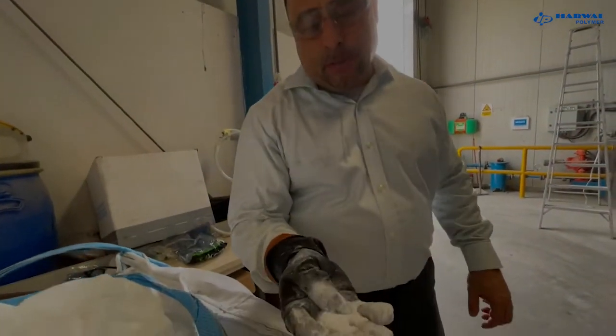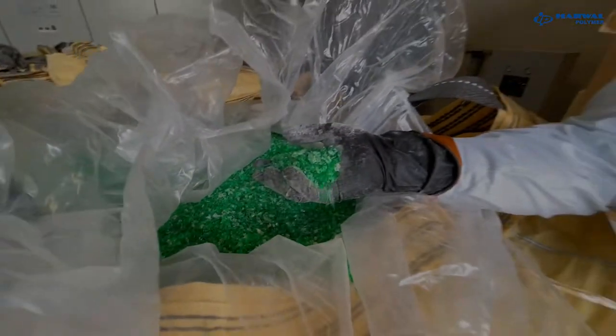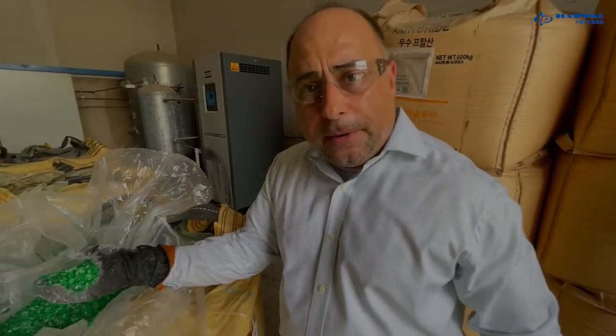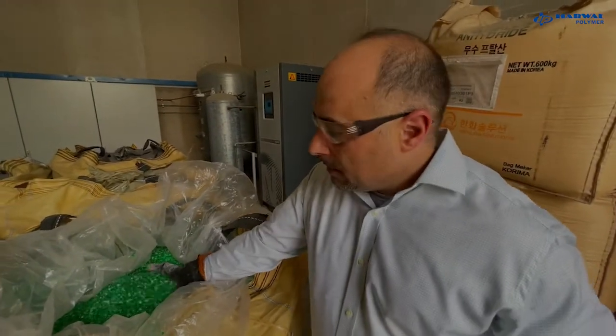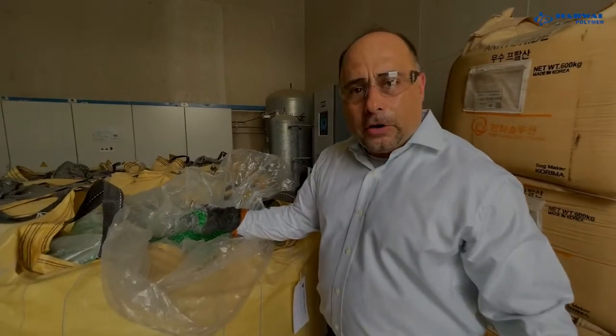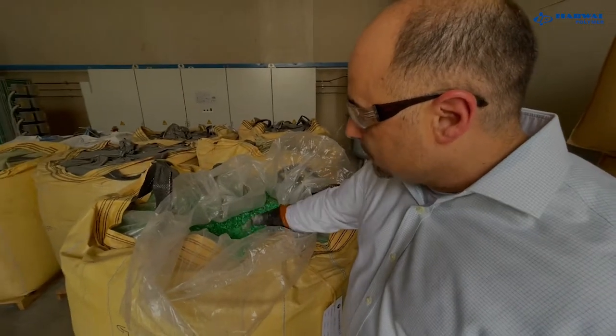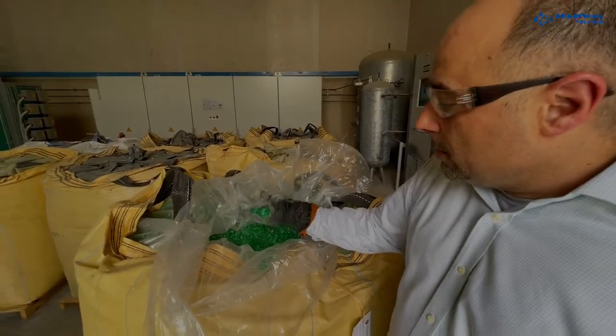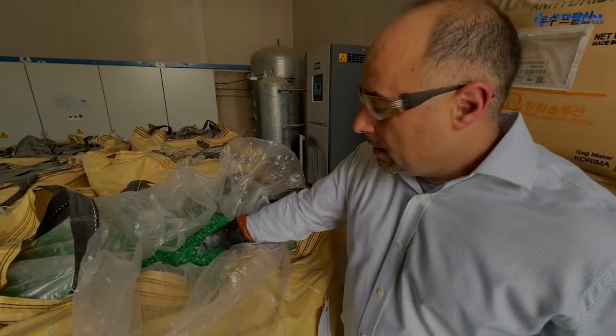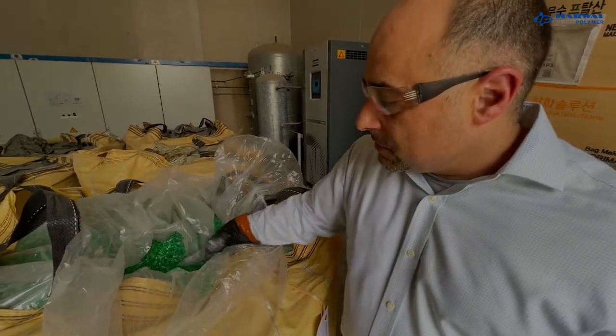As you can see, adipic acid is a powdery product that comes in big bags and we use it in our production. What we are doing right now is converting crushed PET preforms — which you see in my hand — to make PET polyol. We put them in glycol and other elements and convert them to a commercial grade polyester polyol. The good thing is they're dense, so our cycle time is faster because the material loads faster into our reactor.